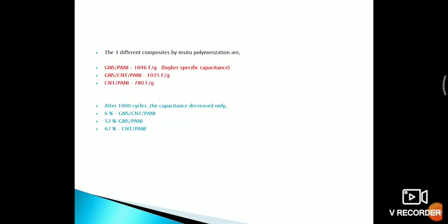The three different composites by in situ polymerization are: first, graphene nanosheet polyaniline composite, which showed specific capacitance of 1046 farad per gram; graphene nanosheet CNT polyaniline composite shows 1035 farad per gram specific capacitance; and CNT polyaniline shows 780 farad per gram. Among these, the higher specific capacitance is shown by GNS polyaniline composite. And the cycle stability is seen as, after 1000 cycles, the capacitance decreased only 6% for the GNS CNT polyaniline composite, 52% for GNS polyaniline and 67% for CNT polyaniline composite.